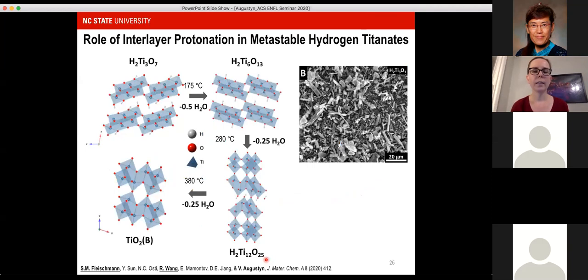So the nice thing about these titanates is that you start with the most protonated version of the material, the one that goes directly from the sodium titanate to the hydrogen titanate, and then you can go again through a series of structural transitions during the dehydration process, where what you remove is actually both hydrogens and oxygens, and so both protons and oxygens. And these structures become more and more dense as you remove water, so that the final material is TiO2(B). All of these materials are fairly large particles, micron scale particles. These are not nanostructured materials.